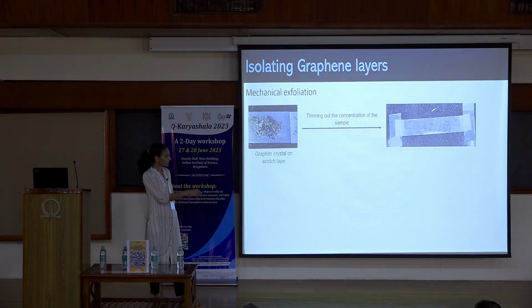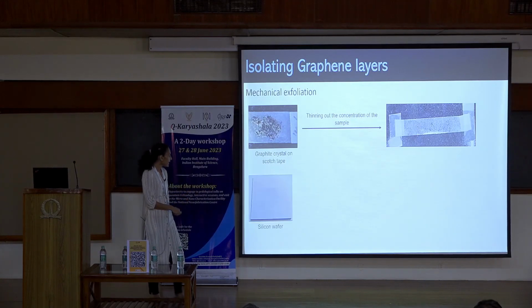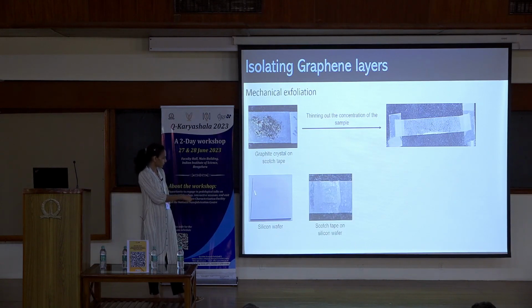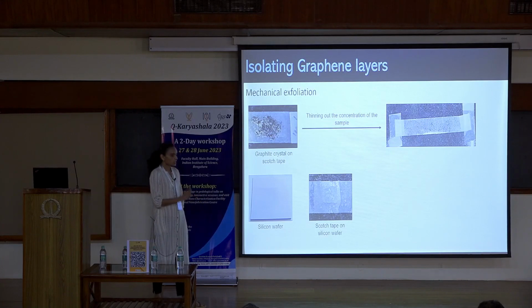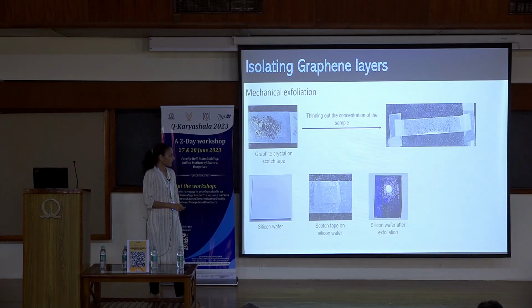Now what you can do is, so this has still got very large chunks of graphite in there, and you take another clean wafer and you transfer this tape onto it. So this is a wafer, I put this tape on top of this, so you can see the wafer is somewhere here. You rub on it for some time and then you peel out this tape, okay? So you have this wafer after exfoliation. Somebody took a photograph from the lab, that's why you see a flash, but it looks dirty with some pieces on top of it.